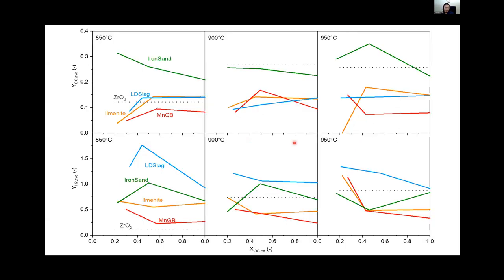And this slide compares the CO and hydrogen yield from the gasification process with all the oxygen carriers at 3 temperatures. But again, the LD slag and iron sand have the highest gas yield.